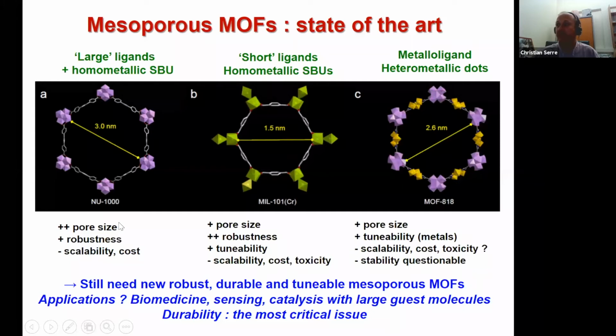This is efficient to produce a mesoporous solid, and you are still having a good chemical stability because zirconium carboxylate are relatively stable in the presence of humidity. But the ligand is not easy to scale up above a few gram scale and is very expensive. So it means that for some application, it's not a problem if you need only a little bit, and then it's a high value application. But for other application, it's totally irrelevant to consider this material for a real application.